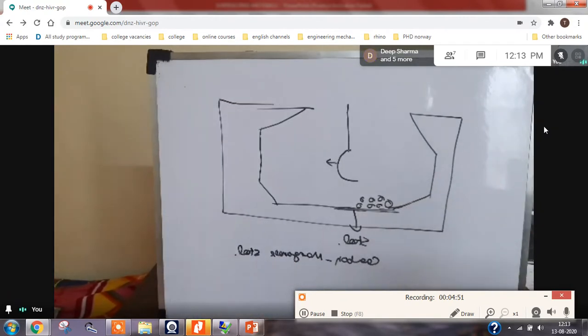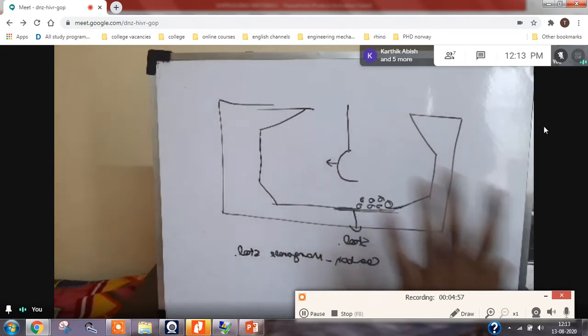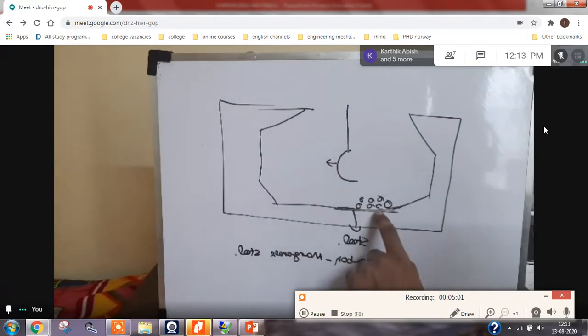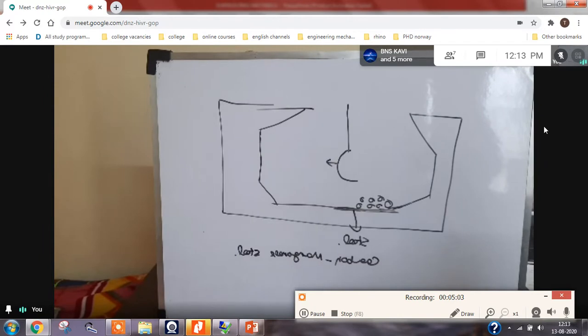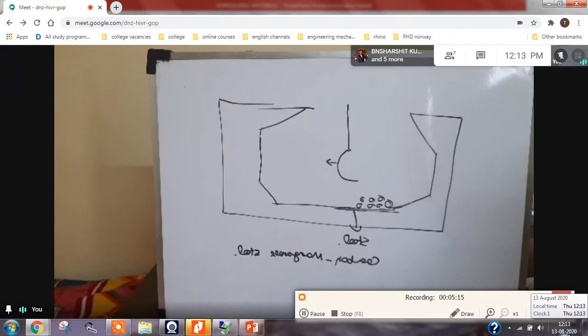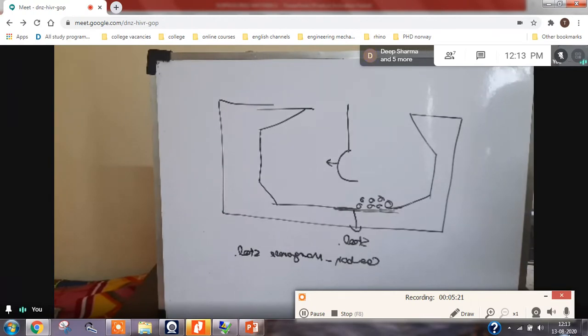Carbon manganese steel, what is the disadvantage? It is very prone to corrosion and the toughness is very low, but the hardness and strength are very good. We increase the carbon content and use it in these places. Wherever you need hardness, the carbon content is higher. Understood? So that is one application. You have to think which part of the ship is going to undergo which kind of stresses. Based on the stress, if it is tensile or compressive stress, you go for high tensile steel. If it is going to undergo abrasion, you go for hard steel, meaning more carbon content. Clear?